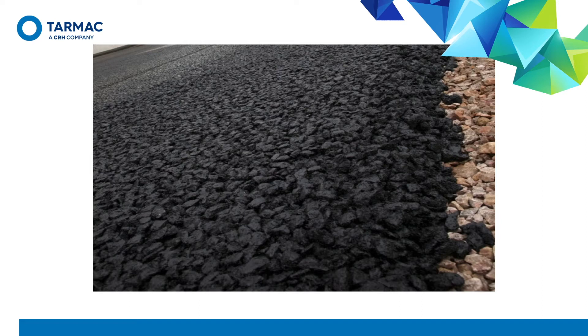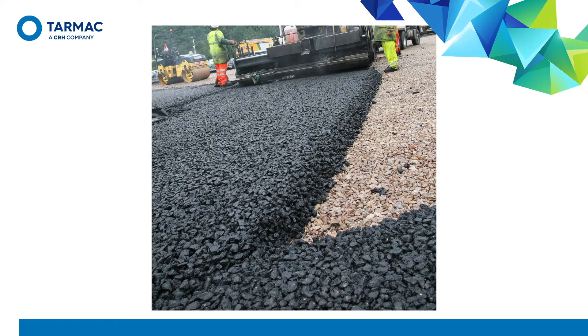Aggregates with good affinity with bitumen are preferred, and it may be necessary to use an adhesion agent in with the bitumen to give high performance. Tarmac uses porous 32 mm base and 20 mm binder course mixes, which typically deliver around 20 to 25 percent voids. Between a conventional two-layer and three-layer system, it does make sense to have surface course plus a thick binder course, so something like 30 plus 90 millimetres, in which case you'd do the binder course in 32 mm because it's 90 mm thick. We've developed enough experience in Tarmac with the base and binder mixes to follow broadly a recipe approach, so we reserve the more complicated design process for surface courses, which can be 6 mm or 10 mm stone size depending on end use.